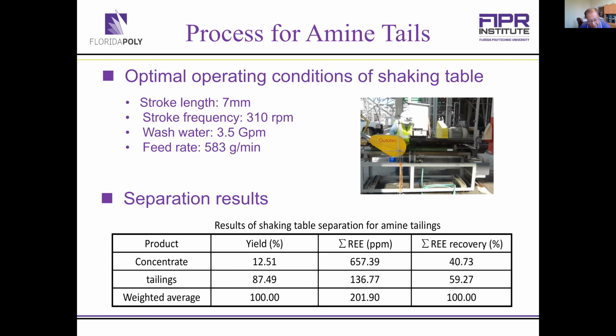Again, this is a pilot scale shaking table. As you can see, just by this one stage flotation, gravity separation, we concentrate nearly 40% of rare earth elements in only about 12.5% of the mass. So that's a very good separation. The rare earth concentration is increased from about 200 ppm to 657 ppm in the concentrate.